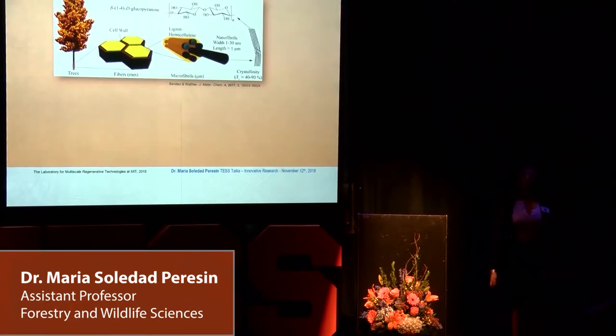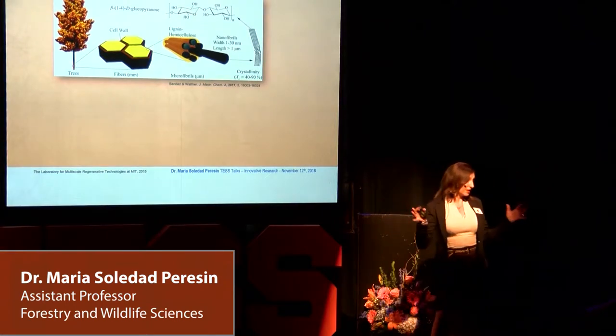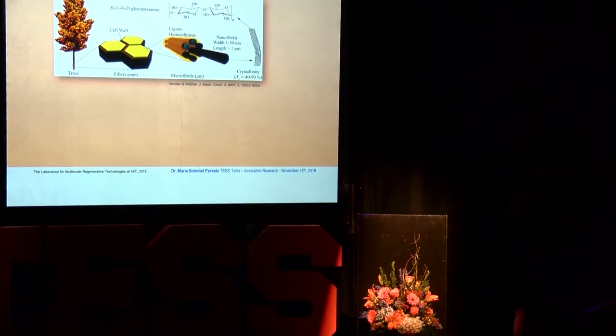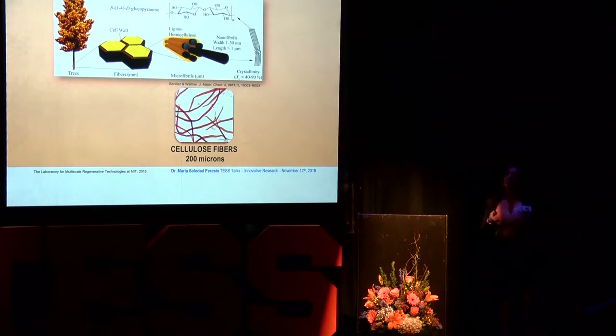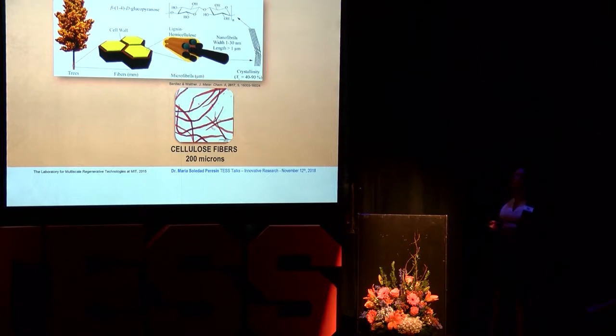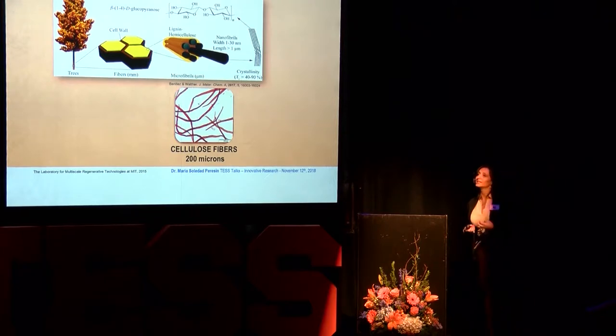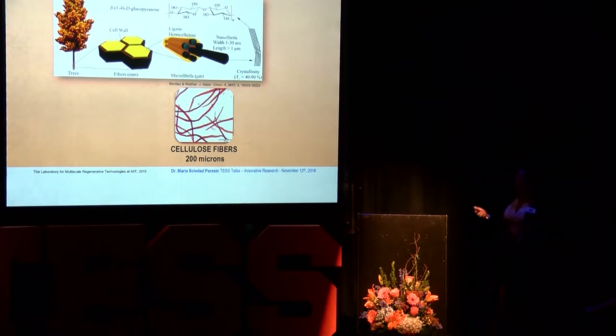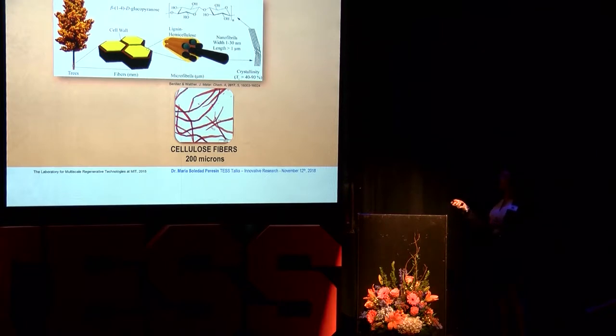This nanotechnology can also be applied to biomass. In the case of trees, we start with the macroscale timber tree, then break it down into smaller scales and reconstruct the cell wall. We find elementary fibrils that are basically made of a polymer called cellulose, which is the structural component of the tree, and it exists at the nanoscale. These nanofibrils are packed in different ways, more or less crystalline, and they form cellulose fibers — cellulose fibers — at the micron scale.